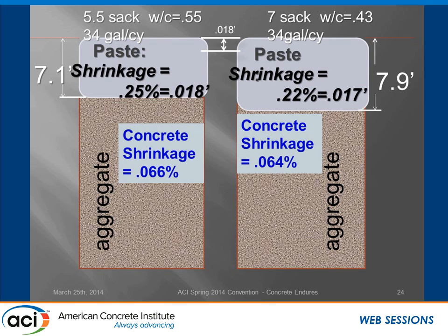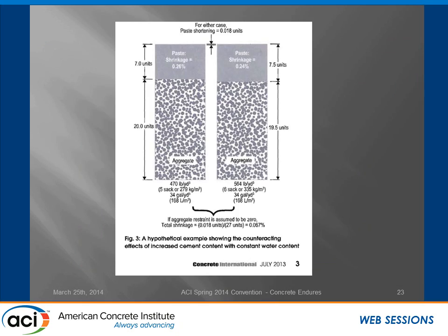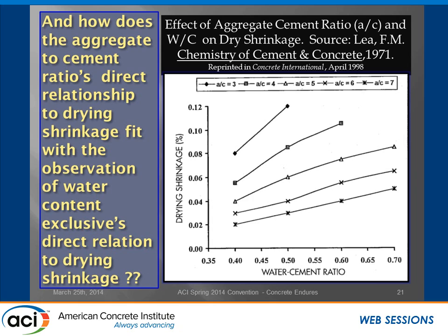If you look at this right here, you'll see that doing the same calculation and pulling off the same values from that same curve I showed you earlier, you can't just lower or raise the cement content and come up in advance with what the shrinkage might be. Here, a 7-sack mix, although it's slight, shrinks less than a 5.5-sack mix. That's the way that worked out. I want to go back to this slide. This slide right here, and how does this slide fit in right here?